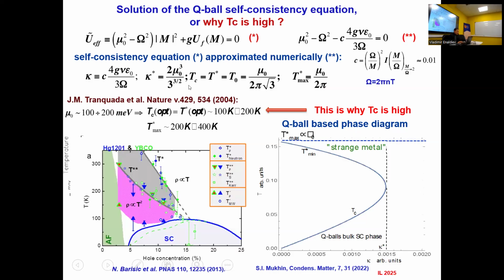You see, this is the answer. So when Tc touches T star, the value is just mu sub 0 over 2 pi square root of 3, and the maximum T star at which the first Q-ball appears is this one. So this mu sub 0 is known from John Tranquada's experiments on spin waves in doped high Tc cuprates, and it gives you inverse correlation lengths because he measures the width of the resonant peak for spin waves, and it's indeed around 100, 200 kelvins, and that's why Tc is high, because you see that the highest optimal Tc is of order mu sub 0 over 2 pi.